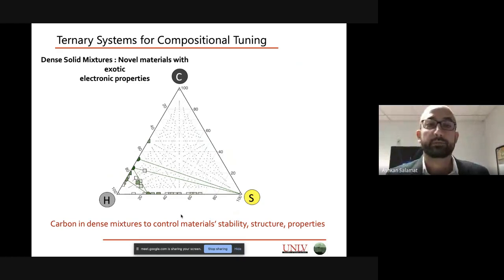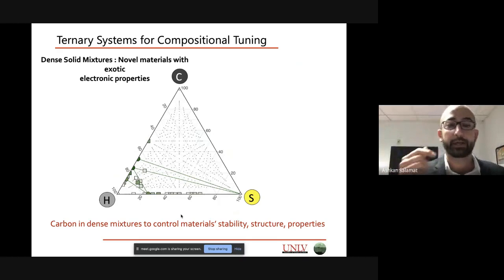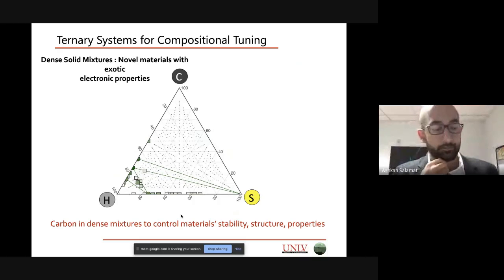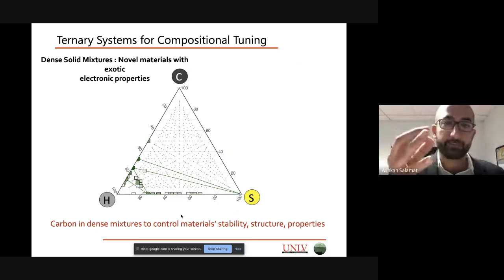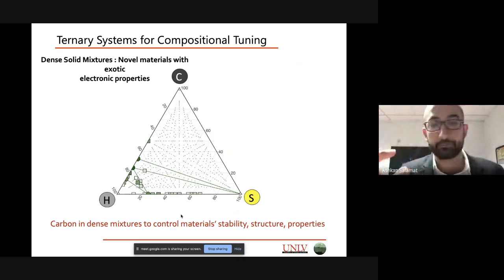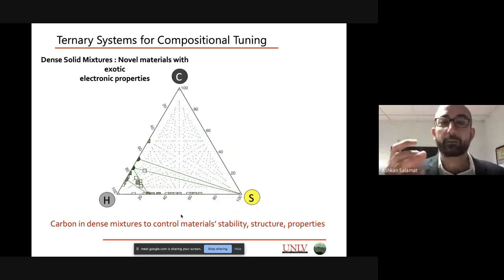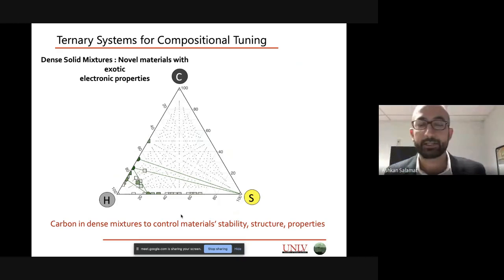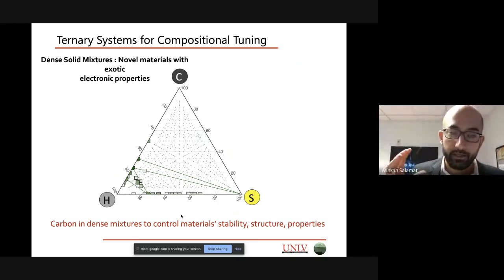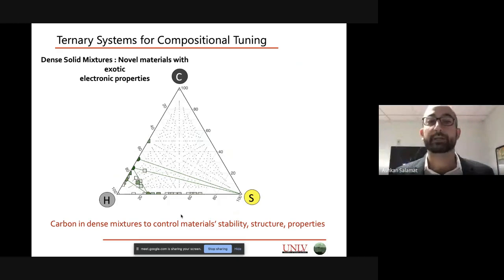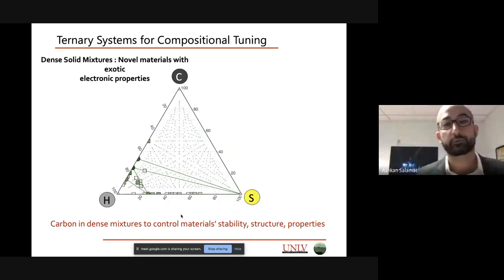And the way we did this is we did something very different to the rest of the community. Nearly all of the community has been working on combining hydrogen with some other elements. We decided to approach it using a ternary composition. So now we add three elements into the mix. We have hydrogen, which is the backbone, the mother matrix, and we add carbon and sulfur into the mix. And this very delicate incorporation of carbon and sulfur has allowed us to synthesize a material that has just the right amount of hydrogens to achieve this very, very high temperature quantum state. And so we've basically doped our metallic hydrogen with carbon and sulfur.